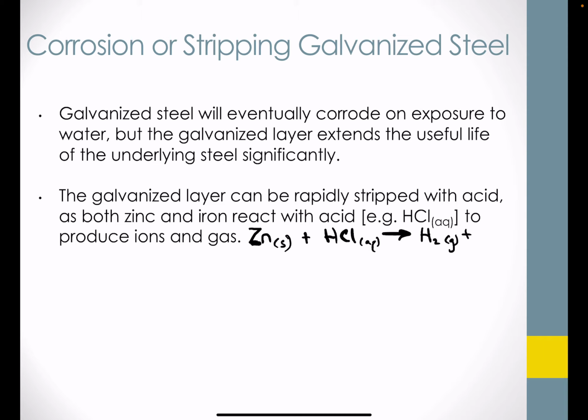Okay, so that's one product. And if you weren't able to determine this product, at this point you could pause the video and see, based on deduction, if you can determine the final product that we expect here. Okay, so thereafter we're expecting zinc chloride, aqueous, as our final product. And the process of balancing here would tell us that we need 2 HCl molecules to give us the dimer of hydrogen and hydrogen gas, and the 2 chlorides in zinc chloride, aqueous. Okay, so that is what happens when we expose galvanized steel and remove the zinc by an acid etch.